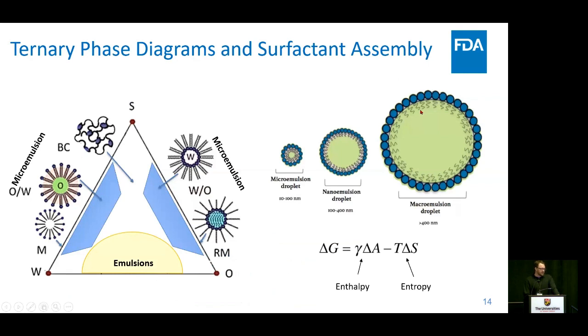So in general, you can kind of think about this in terms of a phase diagram. In order to make really small droplets of something, you have to overcome an immense interfacial energy. So there's two ways you can do this. You can either increase the surfactant concentration, or you can input a lot of energy to try and increase the interfacial area, which means you're making more and more smaller particles. And so in general, the microemulsions kind of fall in this compositional region, and emulsions fall in this kind of compositional region.